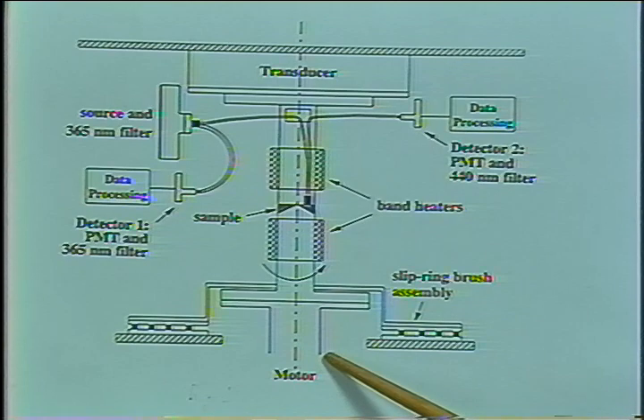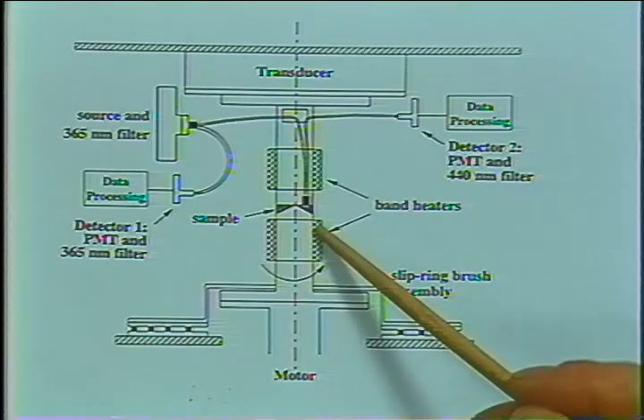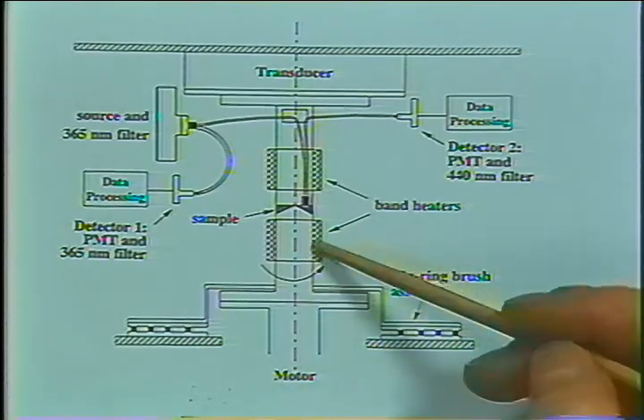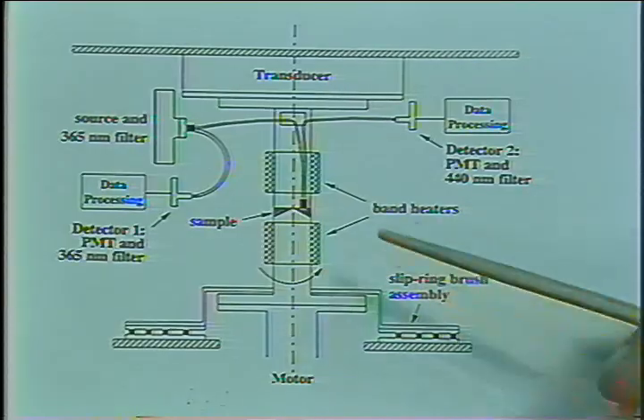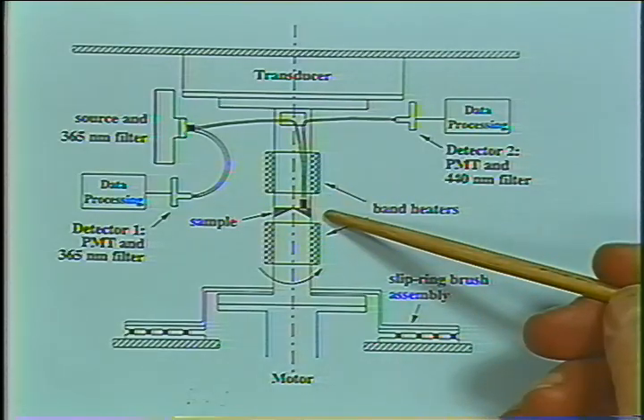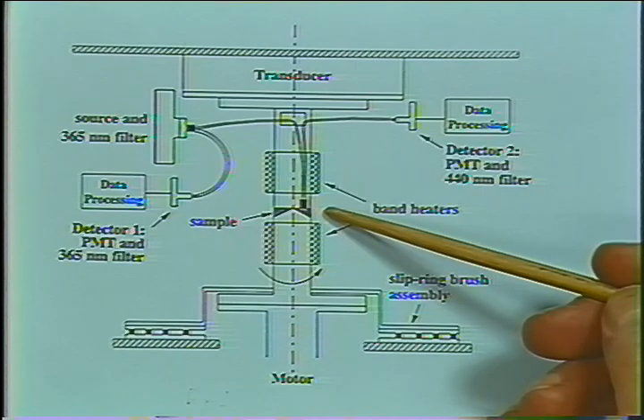So there's a large temperature gradient between your sample and the holder, and there always will be a flux. You cannot prevent a heat flux occurring in the system. You always have to supply heat near the sample to accommodate that flux down the shaft, in the lower region and in the upper region in both cases. And we have to do something about that. On commercial instruments, hot air or hot gas is blown against the sample in this vicinity, and that's okay. It supplies the heat, but the temperature field is fairly inhomogeneous. There also has been a suggestion to mount a heating element in the back part of the plate so that the sample would be heated by doing that.